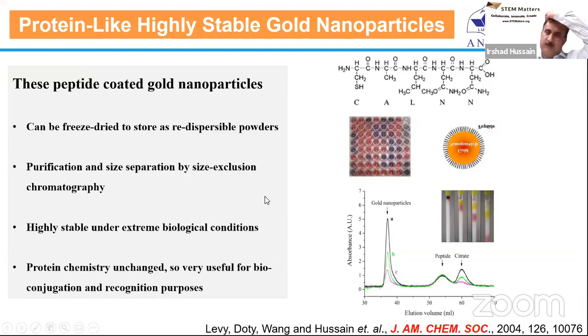As we were talking about the stability of these nanoparticles, that is really important. As I mentioned in the beginning, if they are electrostatically stabilized, the gold particles are not very stable. And they will immediately agglomerate in the presence of a minute amount of electrolyte like sodium chloride. And definitely in the blood, they will immediately agglomerate.